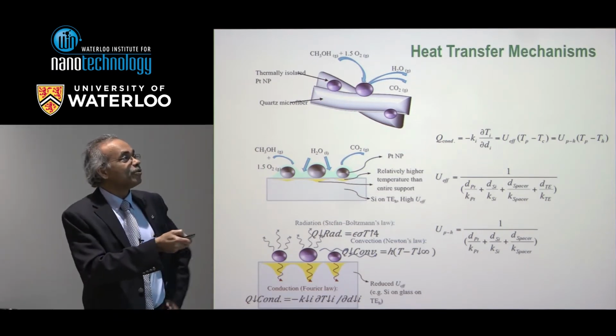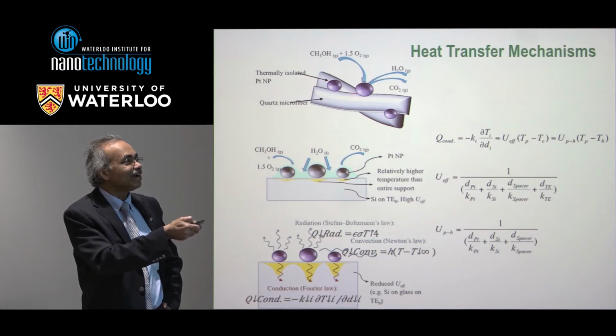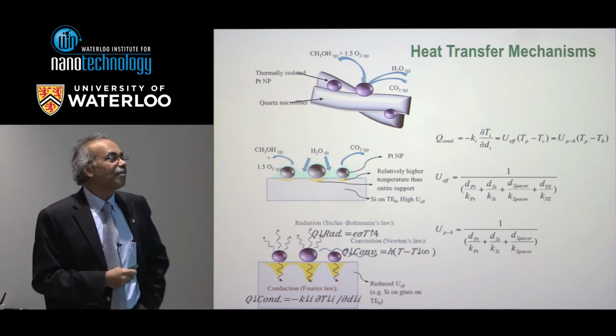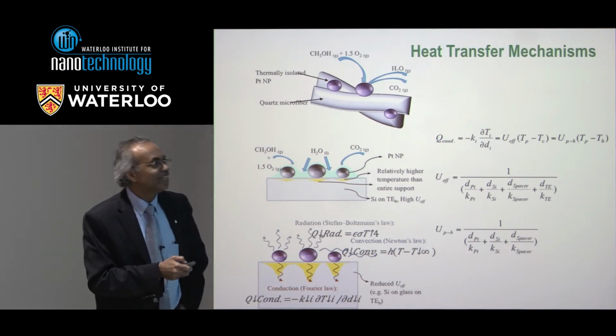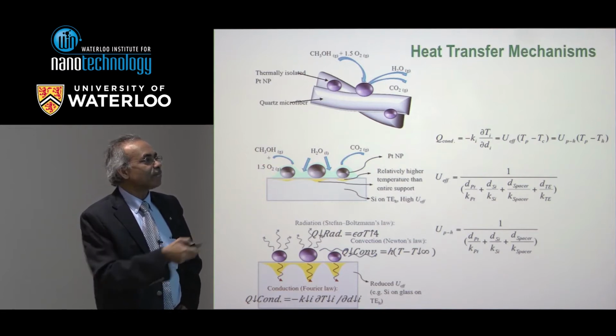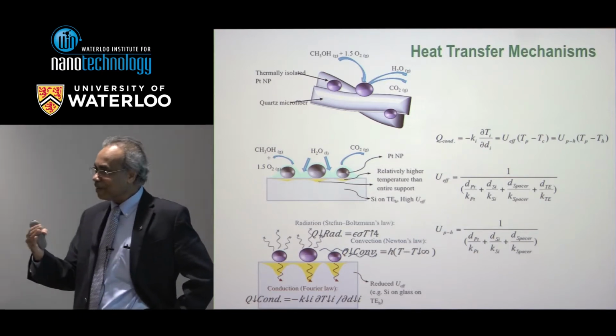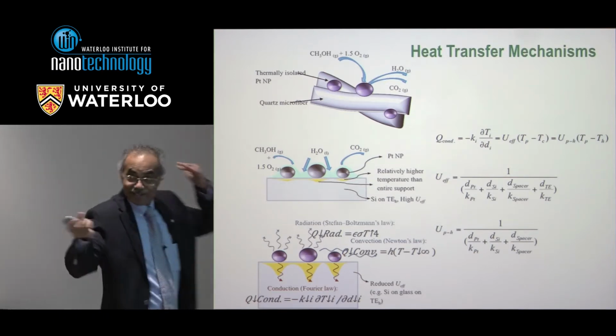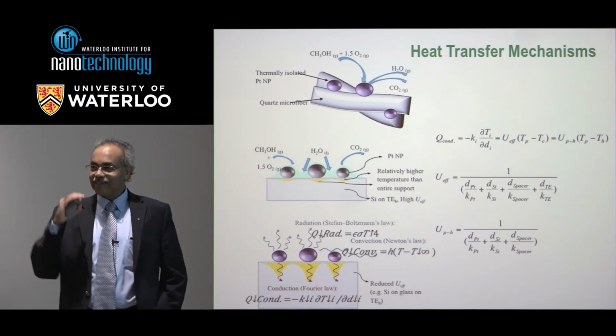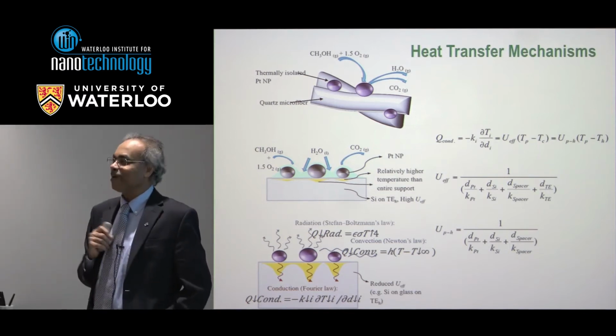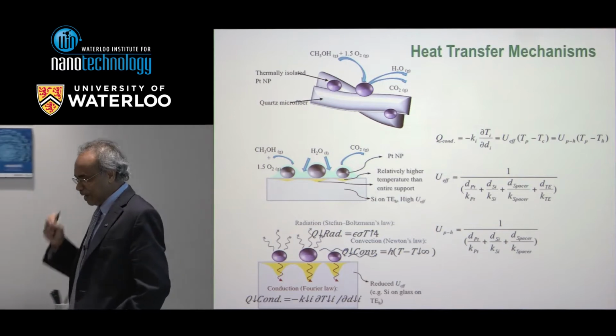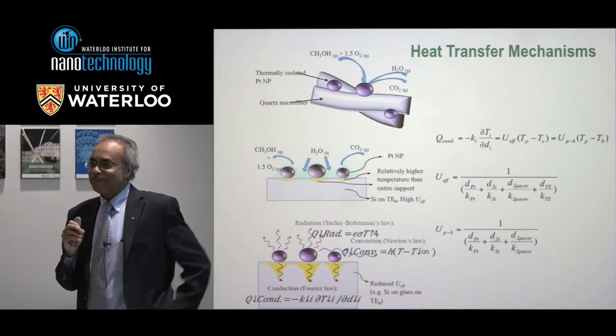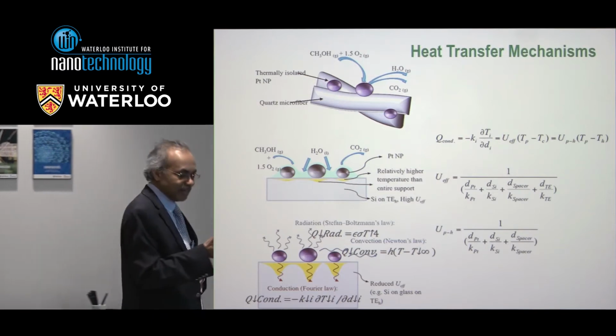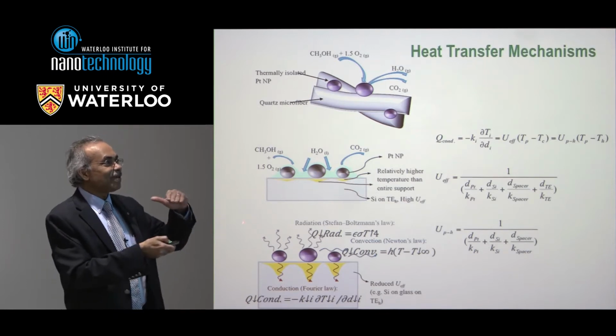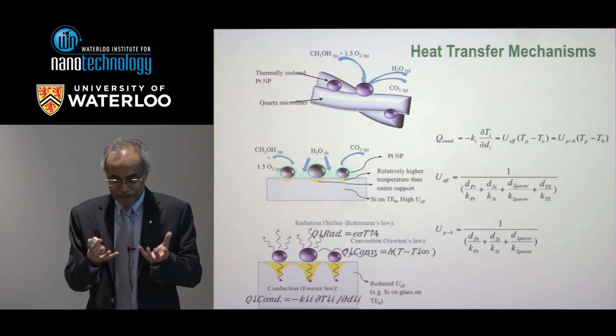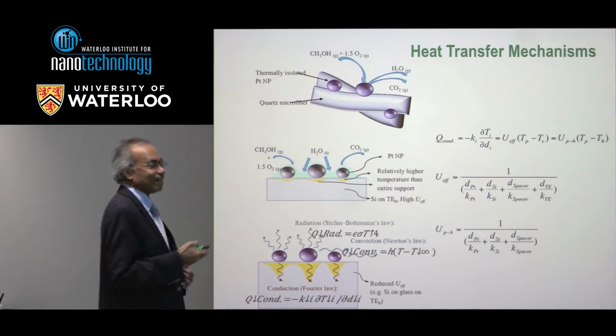Basically what happens is that when methanol is reduced, it produces water, and water condenses right around this tip, the nanoparticle. Just like in an atomic force microscope, you see the capillary condensation. Eventually it covers up the whole thing, and then platinum is no longer accessible to methanol vapor. So basically it kills it. The idea, which actually came also from Sushanta, is to manage the thermal transport across the nanoparticle into the thermoelectric. You have to maintain a temperature above 100 degrees or so, so water wouldn't condense and the methanol will be exposed to the nanoparticle. At the same time, you don't want to heat it too much, because you want the heat to come down to the bottom, to the thermoelectric device.